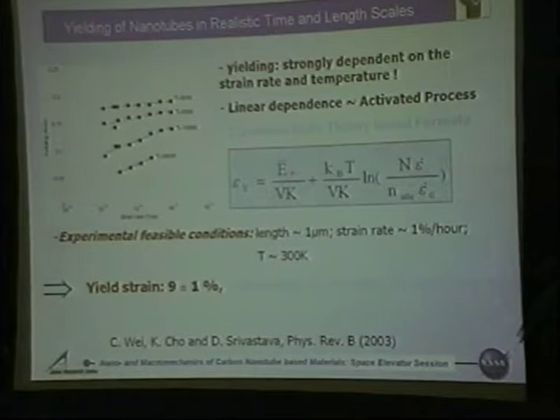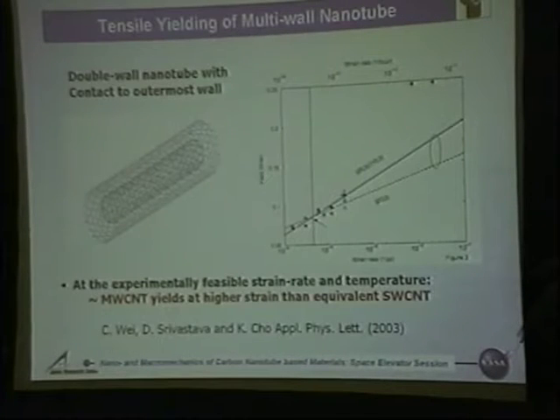When you go to multi-wall nanotube, we extended that model. I will not go into detail how and why we did that. But look at that other chart. These are all published papers, so if you're interested, I can send you some information on those things. It turns out, and this is also the tricky point, that the tensile strength at which the tube will break also depends on the rate at which you stretch the material, the strain rate. If you apply the strain very fast, you're shocking the material, so it will break at a different strain.